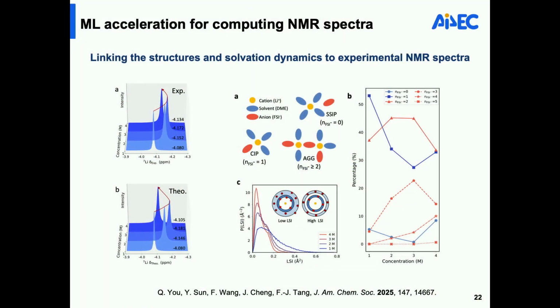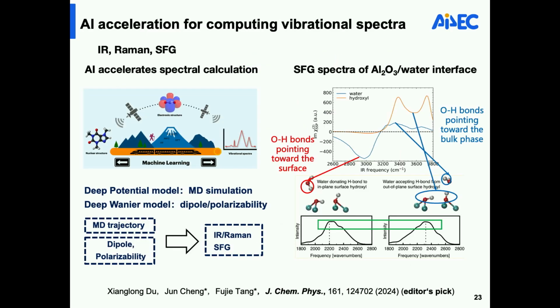In this case, when you change the concentration, the chemical shift really shows a turning point. That's reflecting the really complex change in the solvation structure. But experimentally, indeed, reproduces this turning point. That shows the structure must be sufficiently representative. So that's similar for the vibrational spectra.